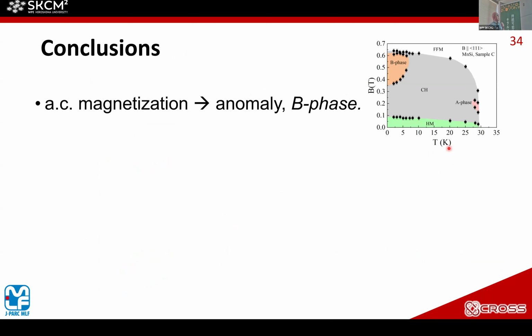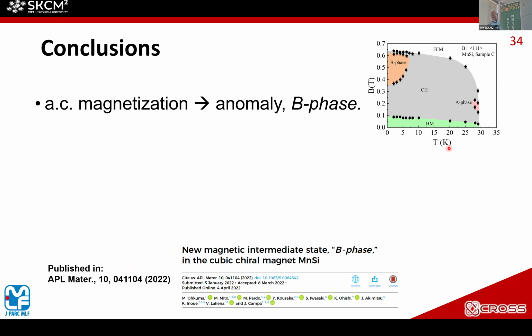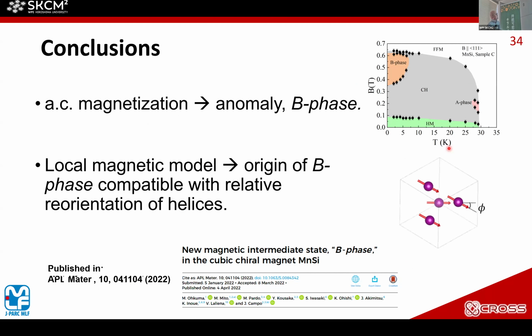So this is my conclusion of the first topic. We have observed the anomaly, B phase, from the AC magnetization, and this is already published. And we conclude that this is the origin of the B phase, compatible with the relative reorientation of helices.